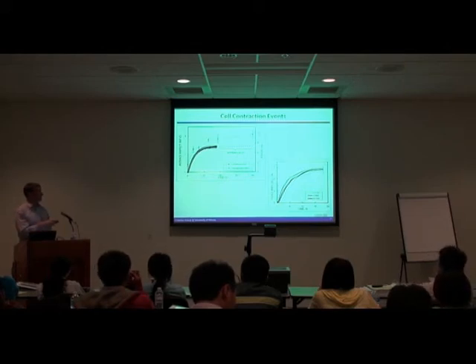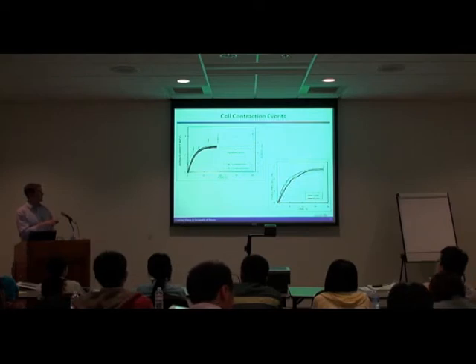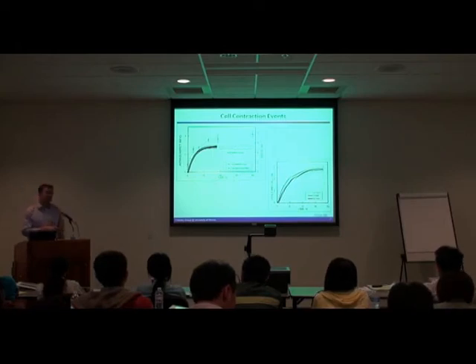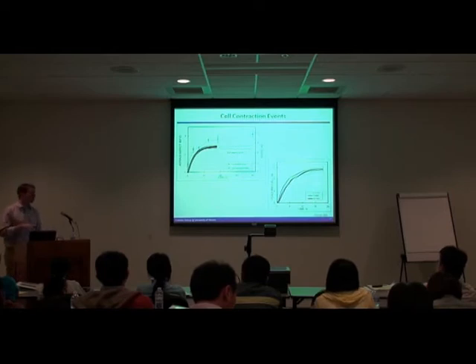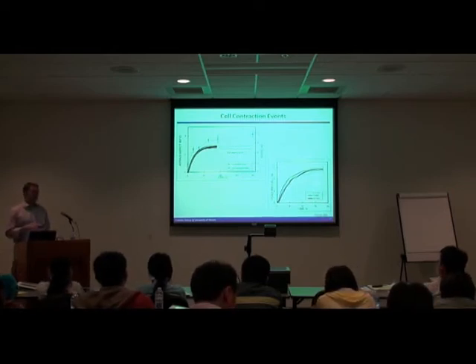So what they saw is they could relate macroscopic changes in the deformation of the scaffold and cell-mediated contraction to actually changes in the local microenvironment of cells. And they could look at the effect of a certain number of cells, or they could actually look at the effect of the stiffness of the system. And what they saw is that when they put these cells into different scaffolds with different stiffnesses associated with them, cells didn't generate different amounts of force. They generated a single amount of force, but you saw different amounts of deformation in the biomaterial.